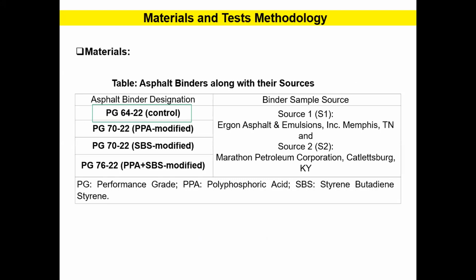In this study, 4 types of asphalt binder are used and evaluated in the laboratory, and these binders are collected from 2 different sources. We use the performance grade PG64-22 binder as a control, because this binder is widely used in the area of Arkansas, and the suppliers are certified by Arkansas Department of Transportation. We also use the control binders along with its modified counterparts, modified with polyphosphoric acid, styrene-butadiene-styrene, and the combination of both PPA and SBS.